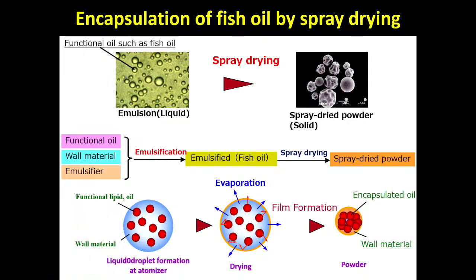And then, in the drying process, first this kind of film formation covers the droplet, and the inside still includes water. The film formation process is very important. And then drying evaporates the water, and we can get the encapsulated oil.